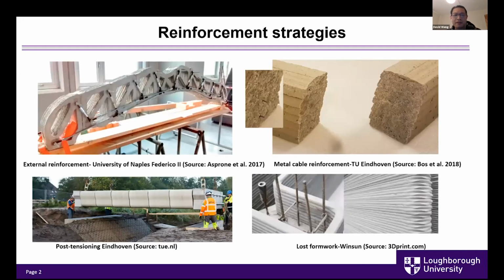One of the most challenging parts for 3D printing concrete is the reinforcement. Several reinforcement methods have been proposed. I have listed several examples. The first one, as we can see from the top left, is external reinforcement. After the concrete is printed, we will use post-tensioning to place all the printed segments together. And also we can try to place some metal cable reinforcement inside the concrete bead. We can also use 3D concrete printing to print concrete formwork. In this case, we are able to place the steel reinforcement or other kinds of reinforcement inside, and then we can cast the concrete later.